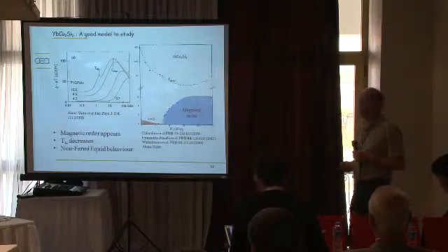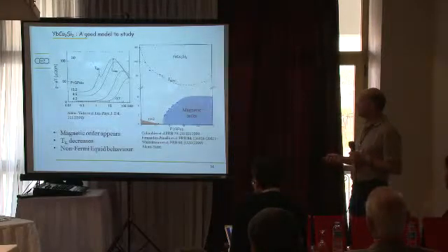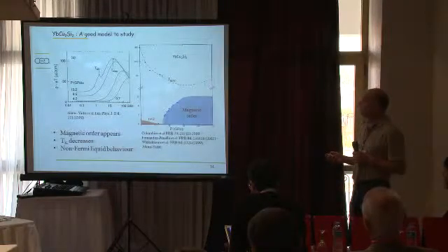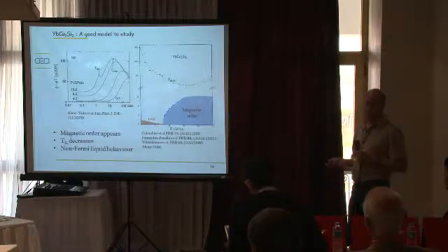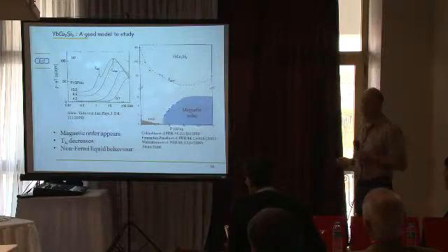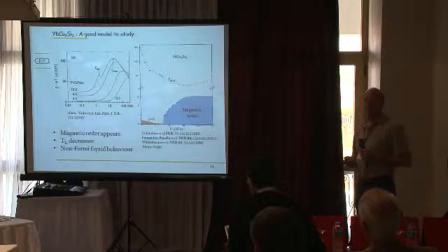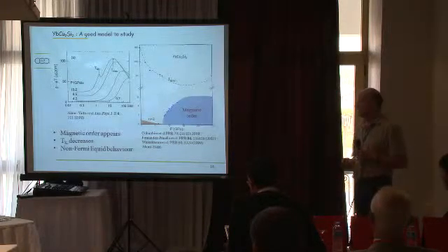And it seems to behave as we expect. More than 10 years ago, it was shown in the resistivity that under quite high pressure, about 8 GPa, a clear anomaly appears, which was correctly assigned to magnetic order. And since then, we have confirmed the phase diagram using many techniques, including specific heat and susceptibility.